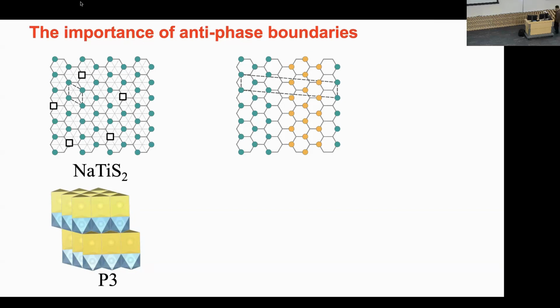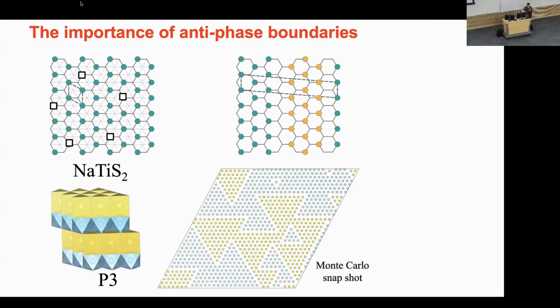That's what's reasonable. But when you map all those energies on a surrogate model, like a cluster expansion, and then go to Monte Carlo, you can look at the pattern formation at much larger length scales, and you're not restricted by these small periodic unit cells. And in that case, what you see is that the favorable antiphase boundary is actually this one, and there are 3 orientations, and that's why you have these 3 orientations over here. And so you get these kind of triangular networks or triangular patterns, kind of fractal patterns. And so this is a structure where you have a whole bunch of vacancies, and all the vacancies coalesce at these boundaries that separate perfectly ordered domains like this.